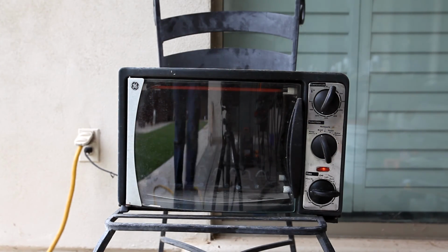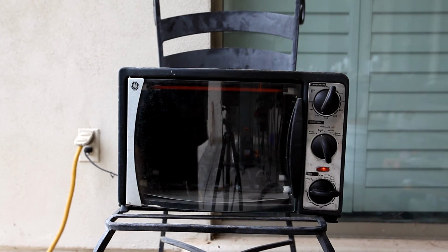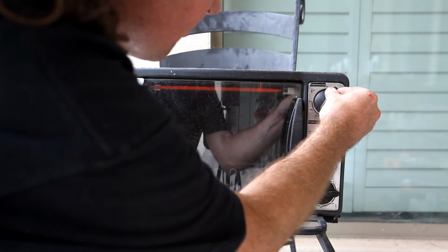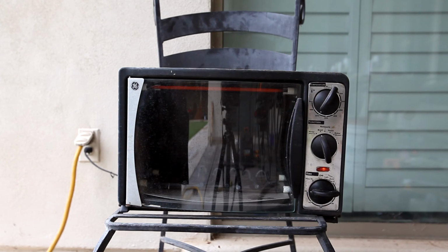So I decided to bump up the temperature to 400 instead of 350. 350 would give me a Rockwell hardness of around 62, and I think that is a bit too hard. On a knife edge that's nice, but these blades are so small and so thin that putting a fair amount of force on them might snap the blade. So I'm going to put them at 400 and double temper that for an hour each, and that should bring the Rockwell hardness down to around 60 or a little bit under. And I think that's probably a better bet for this purpose.